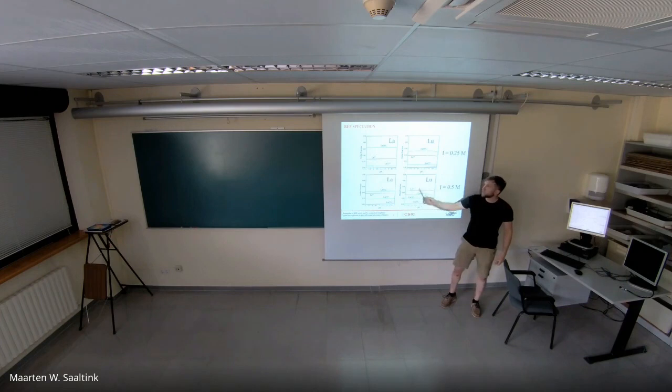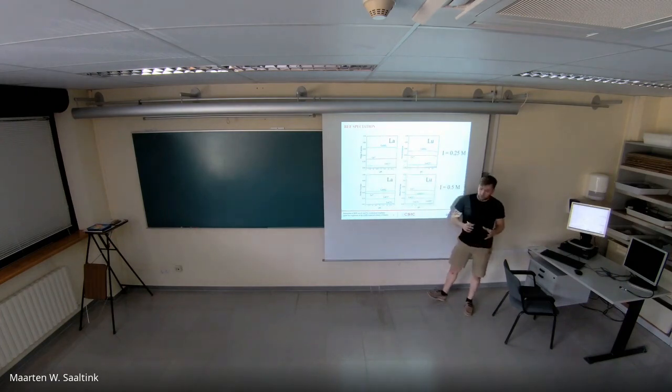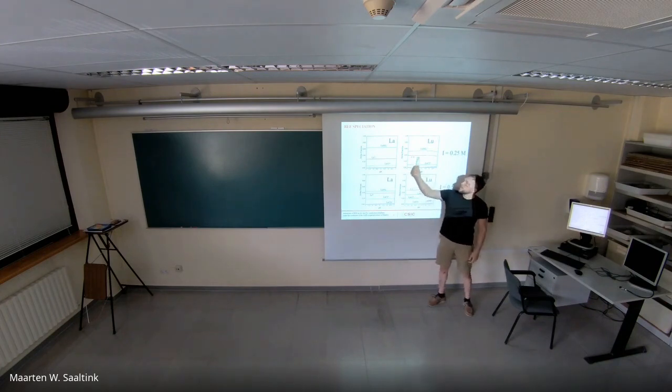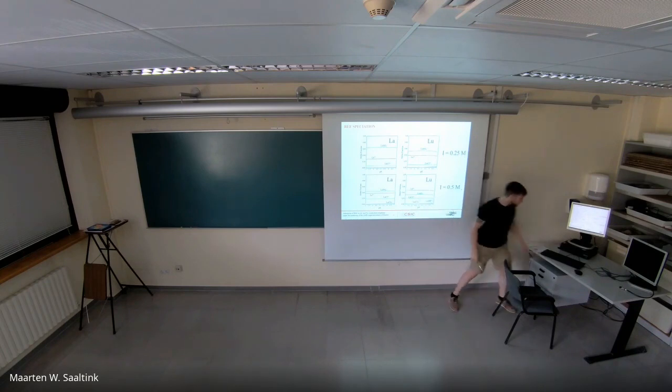The main difference we can see here is that the rare earth element sulfate, which is the species that is adsorbing onto the surface of the minerals, is higher in solution 1 than in solution 2. And on the other hand, solution 2 has higher free ion species and higher aqueous rare earth element fluoride.